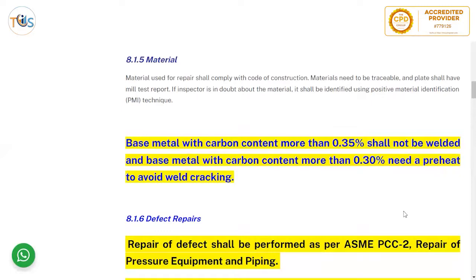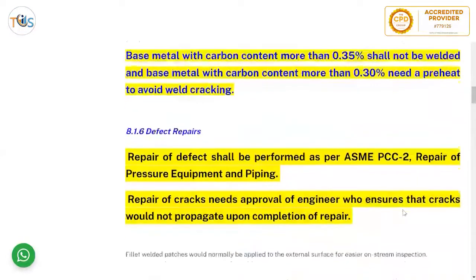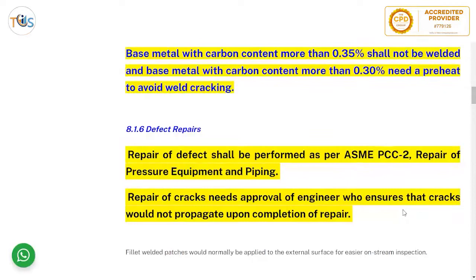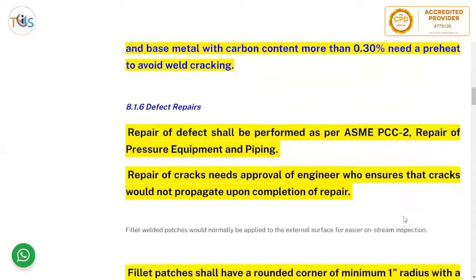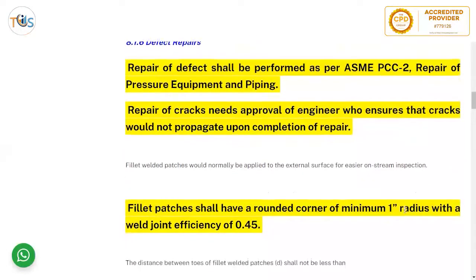Base metal with carbon content. This we already talked about. Again, it is brought in this subchapter. Base metal with 0.35% carbon content shall not be welded, and with carbon content more than 0.3%, it needs a preheat to avoid cracking during welding. So this is repeated twice. Be careful. Anything repeated twice in the codes or recommended practices, there's a high possibility of a question from here.